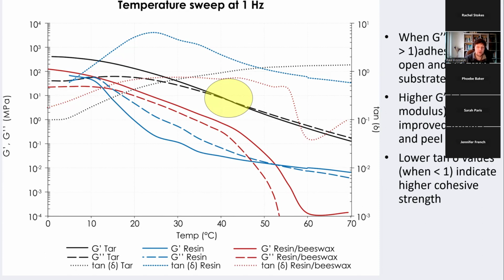In this temperature, for birch bark tar, it's a little bit over 40 degrees. So below this temperature, and it's not going to be a sticky mess. The resin, the pure resin, this happens at about 10 degrees. So anything above 10 degrees and the resin is already sticking to your fingers and being very difficult to apply and to use. The birch bark tar is not like that below 40. The change happens at about 40 degrees, which also means that at 40, 50, or 60 degrees, the adhesive bonds really well and is liquid enough to bond to the materials, but that's still cool enough that you can handle it and press it and shape it. It's not happening at 100 or 200 degrees.